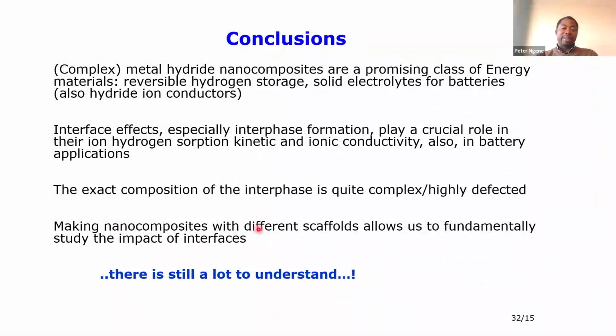If you change the scaffold, we can fundamentally tune this interface effect, and that means we can tune the performance of our metal hydride, either for ionic conductivity in batteries, as a solid-state electrolyte, or even for catalysis, which I didn't show here. Really tuning this interface interaction is key to rationally designing new nanocomposite materials with improved performance.